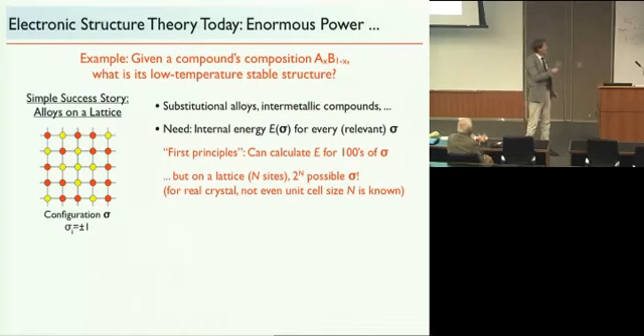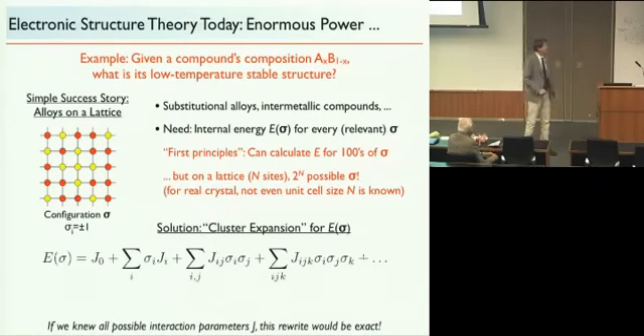So this is a rather large part of materials, in fact. And all you need to solve this puzzle is the internal energy of each of these configurations, because you just find the lowest energy configuration, and that's the most stable structure at a given composition. Now, with first principles methods today, we can calculate hundreds of formation enthalpies for such structures. We might be able to calculate thousands or tens of thousands, but on a real lattice, if this has n sites, the number of decorations of this lattice is 2 to the power of n. So this grows exponentially, and this is a hard problem, even with the fast computers that we have today. Fortunately, there is, in this case, a way to get around the problem and solve it in a more